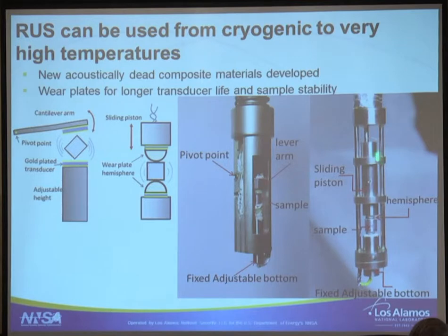This is actually the system that we use in the experiment I'm going to show. And the reason it's all metallic is that these systems can also be used at high temperature. So we can go up to whatever our system can go. In this case, we can reach 900K easily, but of course in this case we went to 30K. And if you just want to do things at low temperatures, then what you do is you build your system with plastics and balsa wood and things like that.